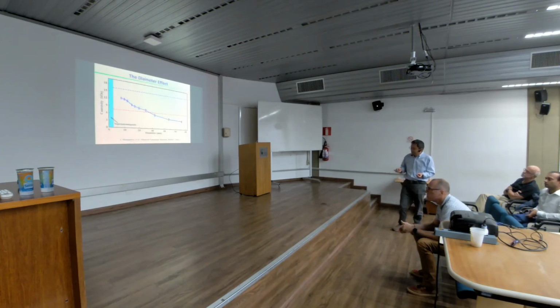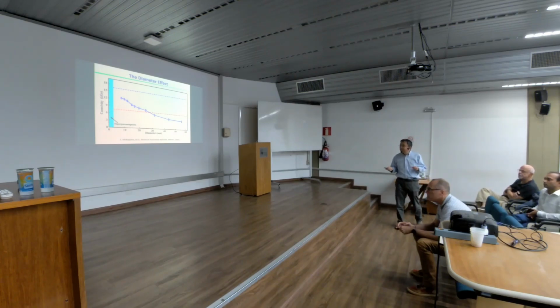Now look at the diameter-dependent coercivity. The thinner, the higher the coercivity. When it's thinner than about 25 nanometers, it crosses the anisotropy field, the red line. It crosses the red line for the first time. What does that mean? That means we experimentally prove the theorem, Brown's theorem.